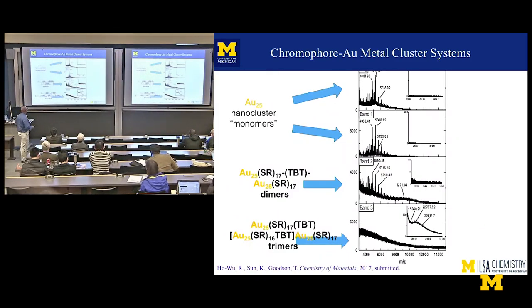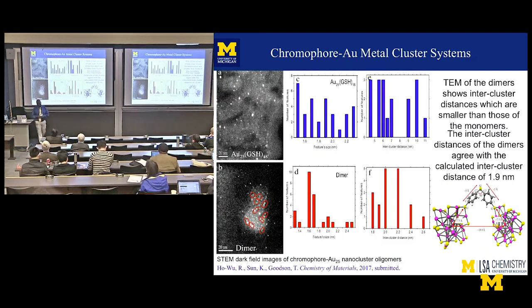The interesting thing, of course, is that later we collaborated with mass spec in our department. And here's where the real genius was, to try to figure out the mass spec fragmentation pattern of two gold clusters with 25 atoms. It's a huge mathematical problem, right? But he did it. We already knew what the gold 25 mass spec looked like, but for the dimer and trimer and other bigger oligomers, he had to go through quite a bit of analysis. And so we found that you could make those.